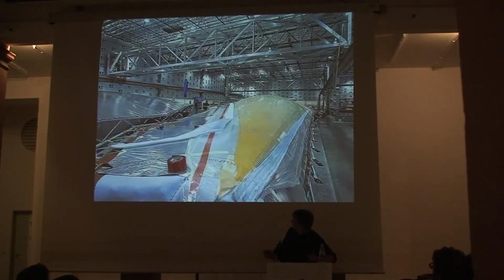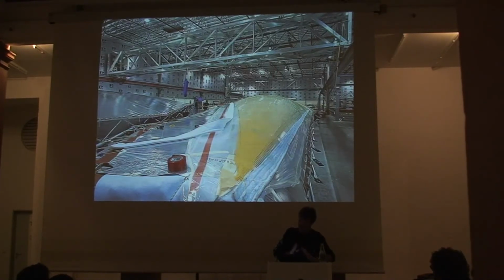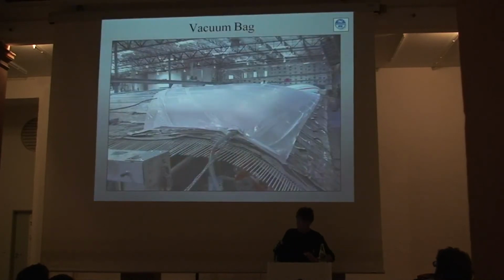So once the fiber architecture is loaded, then they're building a vacuum bag around the sail. So the feature of composites, or certainly these type of pre-preg composites, is that the sail is cooked or heated, and that's done under pressure. And at this sort of scale, you do that in a vacuum bag. On a smaller scale, you might do it in a cylinder called an autoclave, but in large scale, you use vacuum pressure. You suck the air out between the sail. It sucks out any moisture or any solvents or volatiles. At the same time, the films will consolidate all the materials under pressure, and you pass heat over the surface.